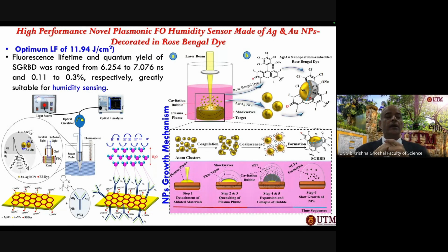In this kind of fluence, we got silver, gold, rose Bengal dye encapsulated particles, and these particles are used to taper the fiber, and then finally we coat the fiber with this kind of colloidal suspension of nanoparticles. And these fibers are used for the sensing purposes of humidity, water.